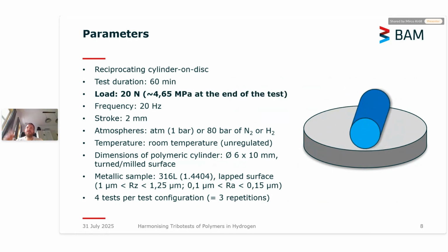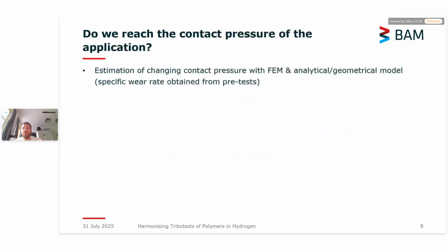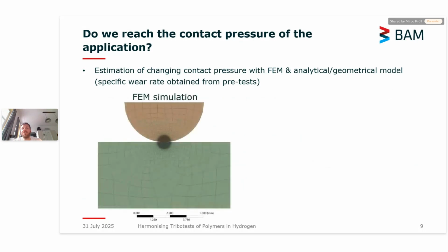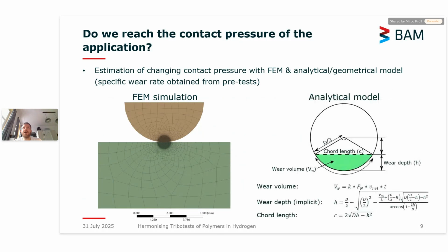Regarding the load, just some words about the contact pressure, because this will change due to wear, because we are testing on the cylinder surface. So we used an FEM and an analytical or geometrical model to estimate the contact pressures. In the FEM model, you have some kind of grid, and parts of this grid are removed due to wear. The analytical model basically calculates the chord length and, via that, the contact pressure. If you like some formulas, there are some, but the story is clear, I think.